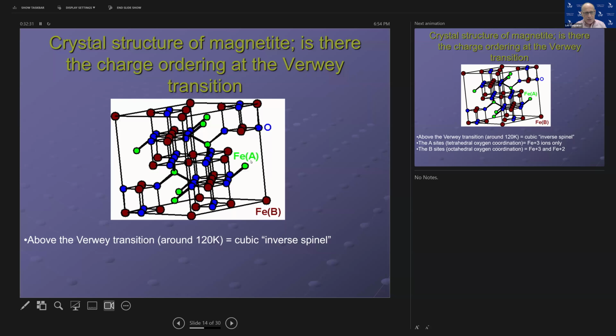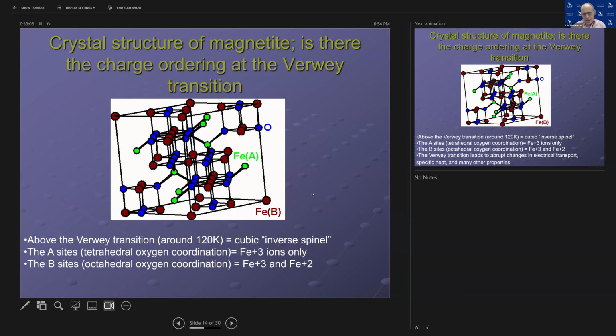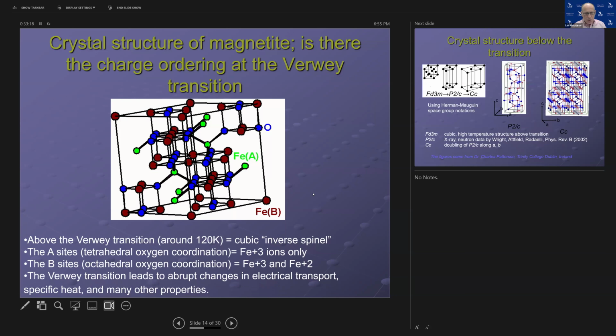So what you have here is the following. You have iron atoms which are in so-called A sites, and those sites have tetrahedral oxygen coordination. The blue circles indicate oxygen. The brown circles indicate iron on B sites, which have octahedral oxygen coordination. The initial idea of the Verwey transition was related to the ordering of atoms on A and B sites, and the understanding was that this leads to the insulating behavior. When the transition happens, many things change in addition to resistivity or conductivity. Magnetic properties change. There is a change in specific heat and many other properties.